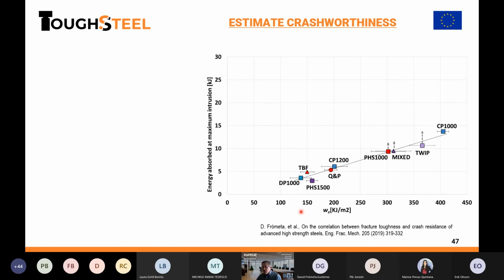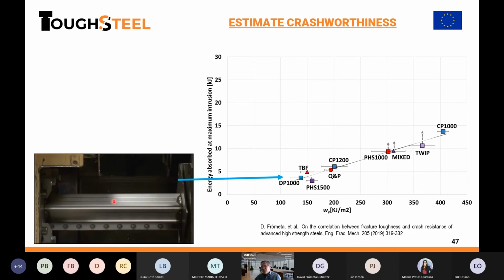Maybe better is another way of measuring energy absorption, that is measuring the energy absorption during crash. In these coupons that we actually crash, we measure the energy and plot against the fracture toughness. Here it works perfectly. We see here two examples.